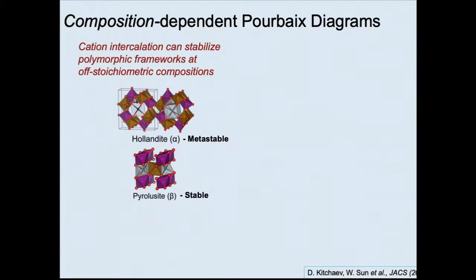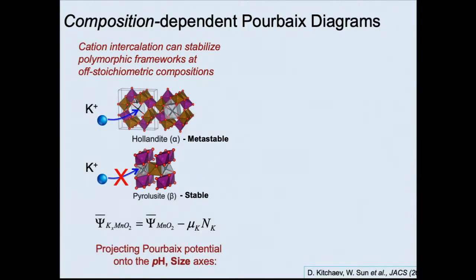Okay. So first thing I do, we set up an experiment with people at SLAC where they do this in situ. So in situ, we put manganese 2 plus precursors in solution. We put a certain amount of alkali in, potassium hydroxide, and we want to see the phase sequence that things go through. So I have to understand the phase stability as a function of the amount of potassium, as a function of the pH, and as a function of the size, right? Because I have to study nucleation. So we do all these factors.